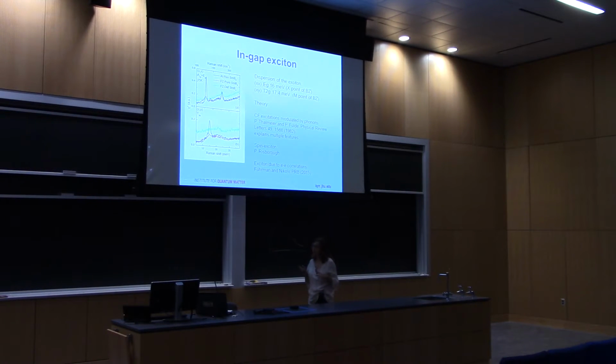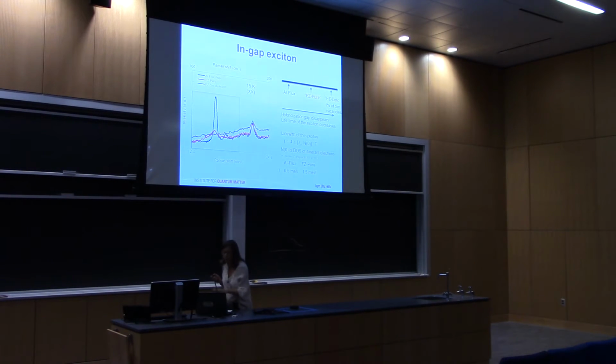So, whatever the nature of this exciton is, it could be for us a measure of how many electronic states we have in the hybridization gap. If you look at low frequencies of our three samples with samarium vacancies, at 1% we don't even have the gap opening, so we don't expect the exciton to be there.